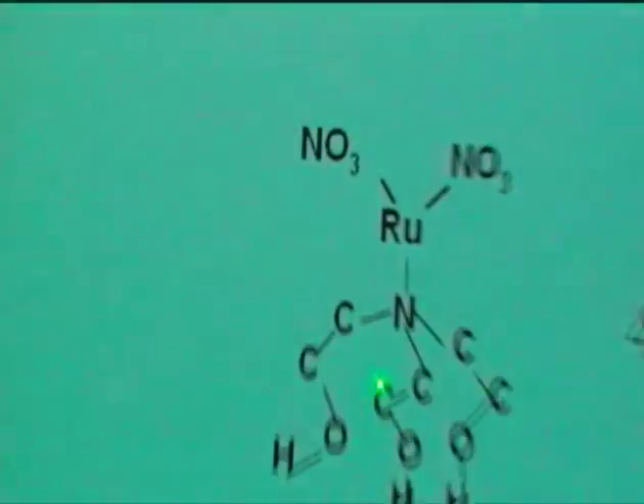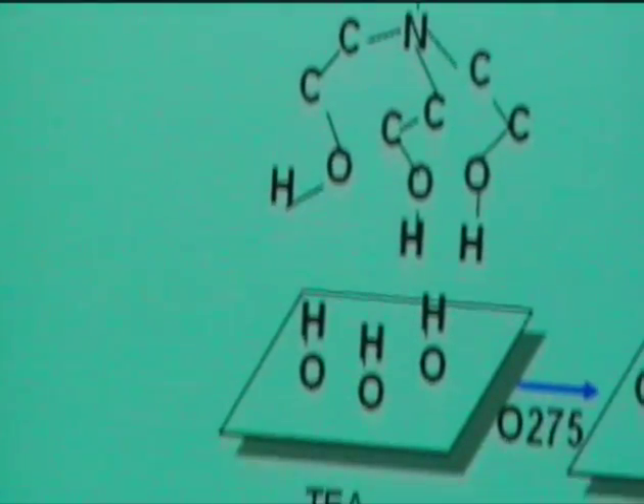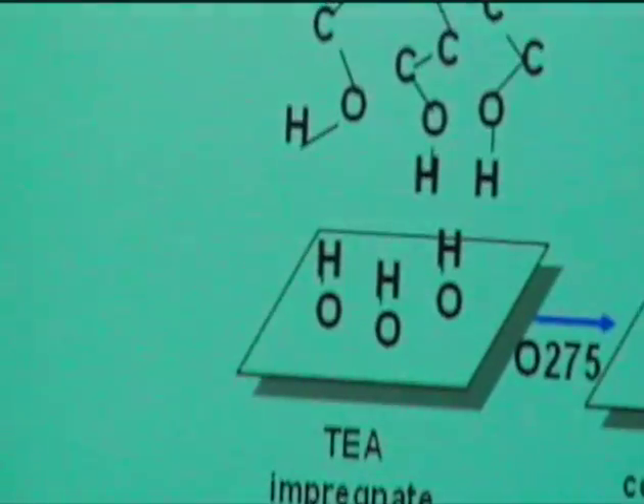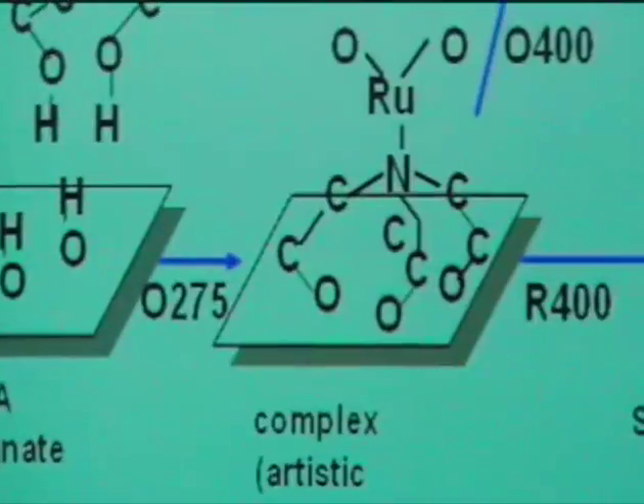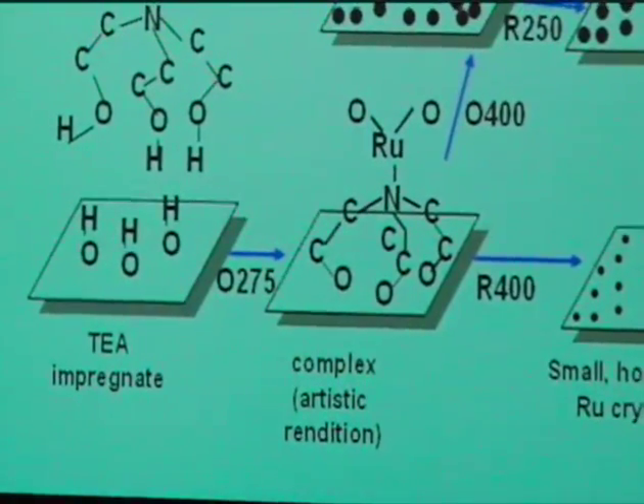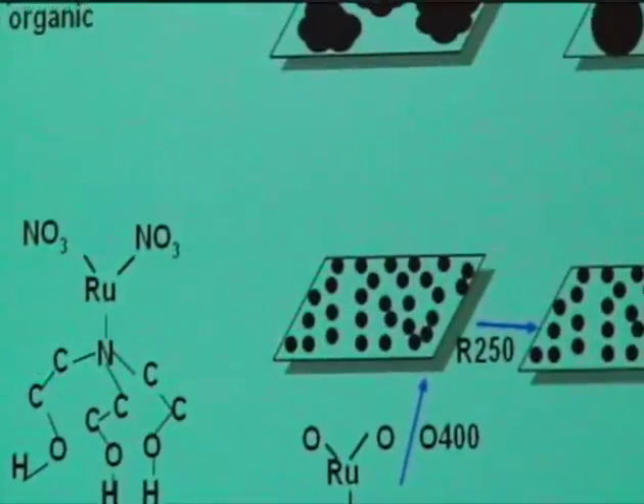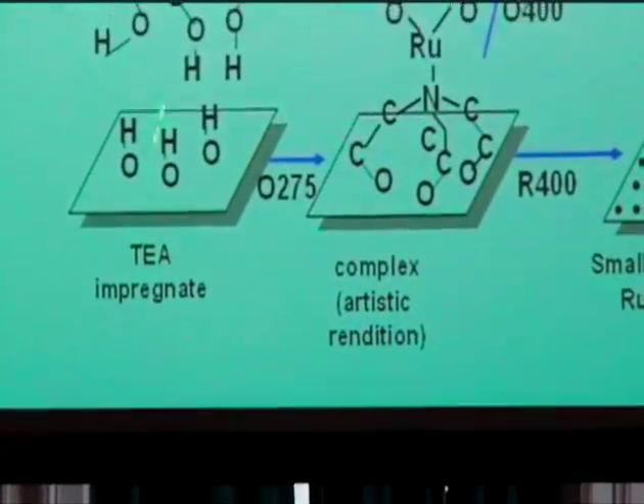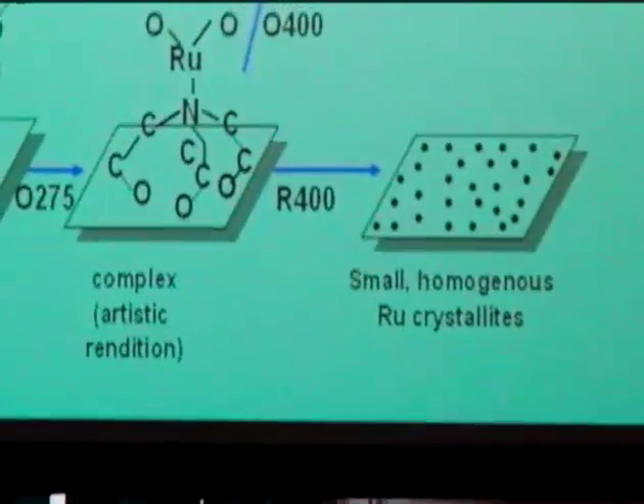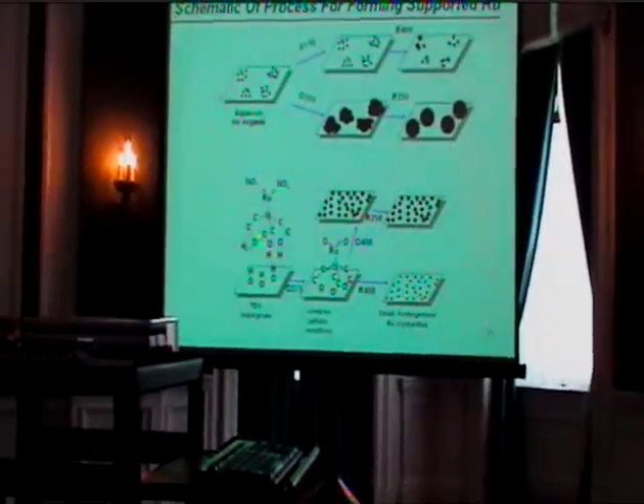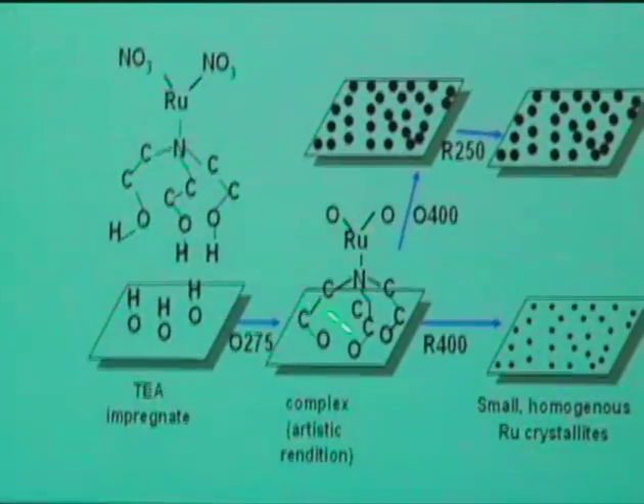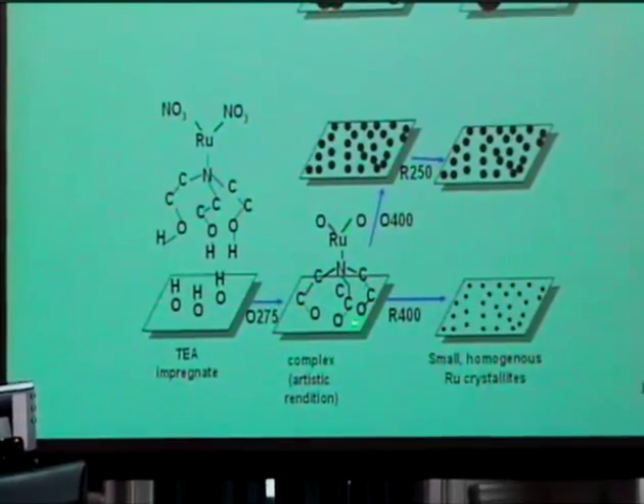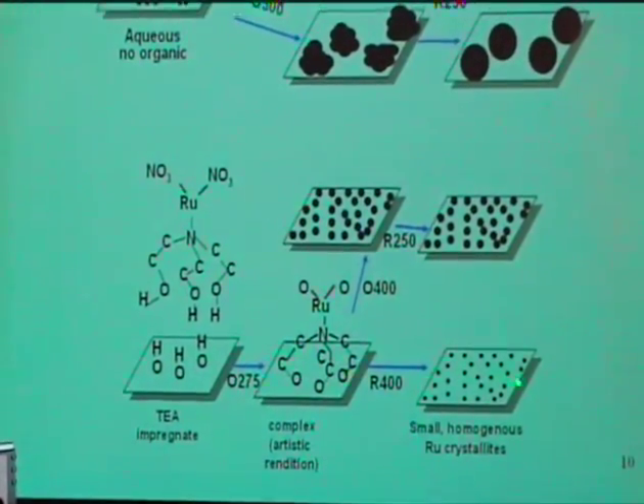Okay, if you go through this complex, and this is just another one of my artistic renditions, but the belief that we have here, and really what we started to work with these, is that we thought that maybe the amino groups could complex with some of the metals, and leaving either the hydroxyls or carboxylates at the other end of the organic to sort of condense with the hydroxyls on the surface, that we might be able to get a different type of control than we were. So we've gotten these complexes, this partially decomposed complex, to interact strongly. So when we reduce it directly, we get that.